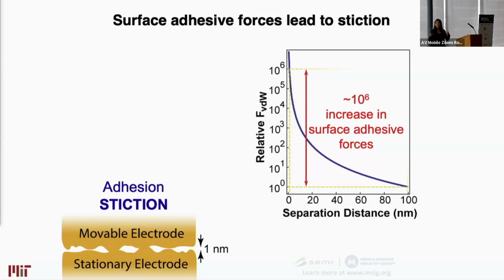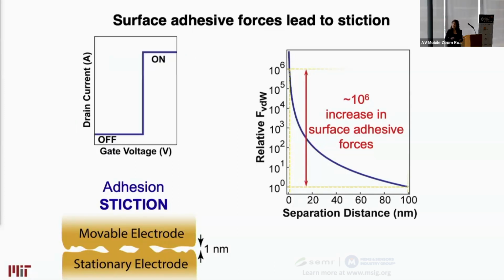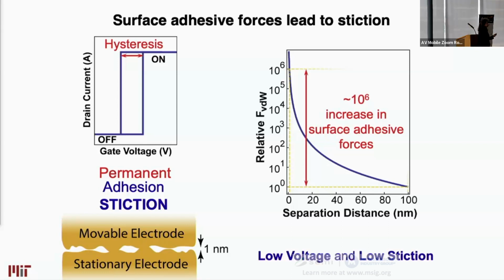Now, that makes it difficult to miniaturize switching gaps. And that's a critical step to move towards energy efficient applications by lowering the switching voltage in these devices. At the same time, this surface adhesion causes the device to experience a hysteresis in operation. And that also sets a limit on how energy efficient you can make your devices. And in extreme cases, the adhesion can be permanent. So you're going to get a premature device failure, which is not ideal.